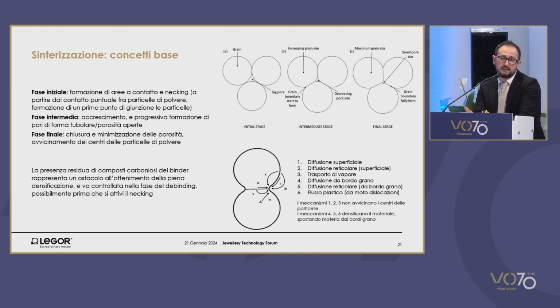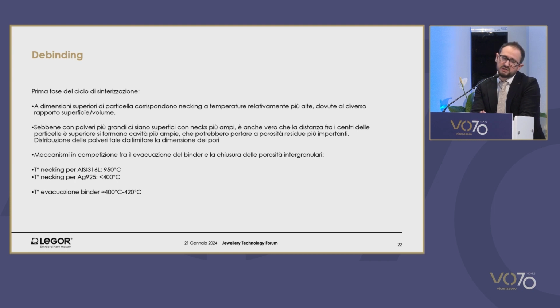So there are mechanisms of surface diffusion that allow us to obtain a meniscus which spreads then in the spaces in the powder, and then as the temperatures further increase, there are some mechanisms in the powder particle that allow for the approximation of the centers of the powder grains so that densification can occur, with the final target of achieving a residual porosity equal to 0 or very, very close to it, very low, that is less than 0.5. For aesthetic purposes, 0.4, 0.3, bearing in mind the distribution of powders, because we're talking about an average value, which is measured in a certain area. But of course, the dimension of some pores could be different. There may not be homogeneity.